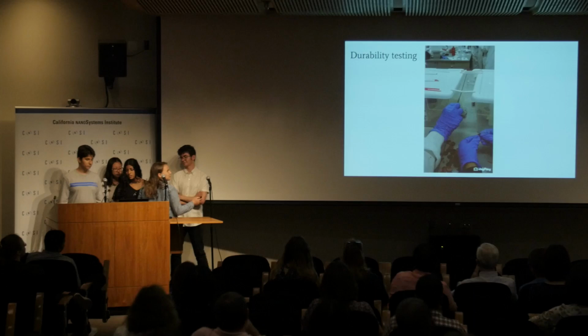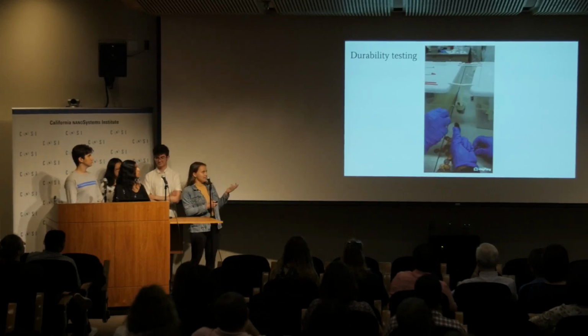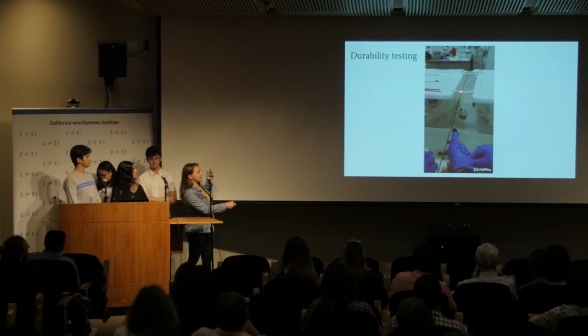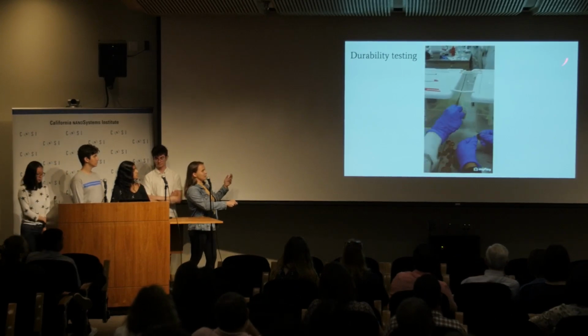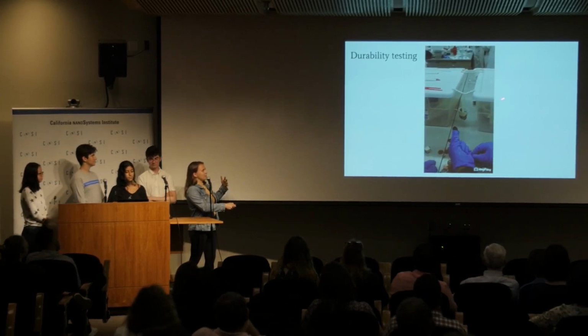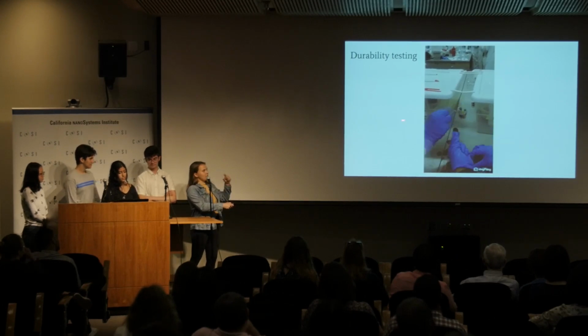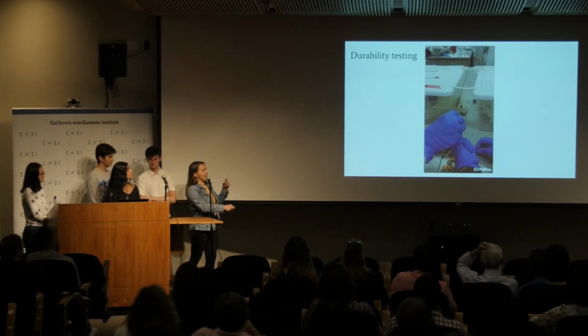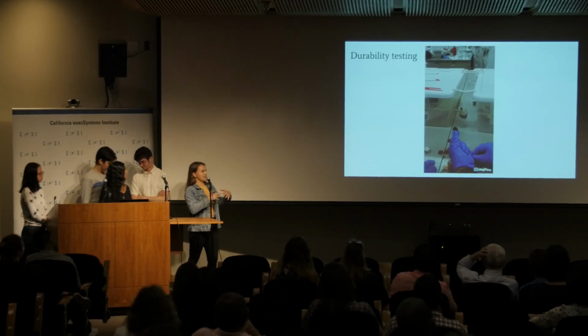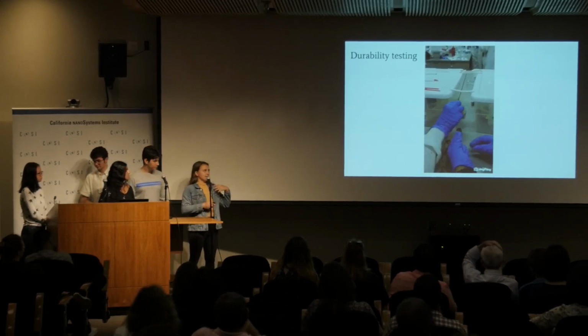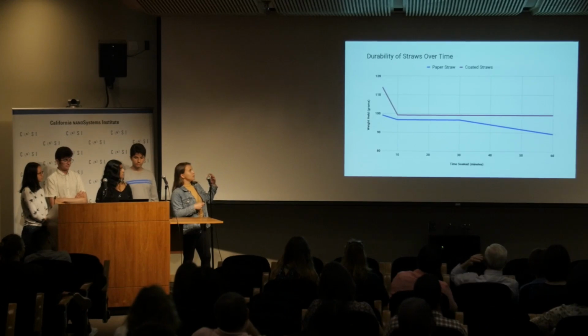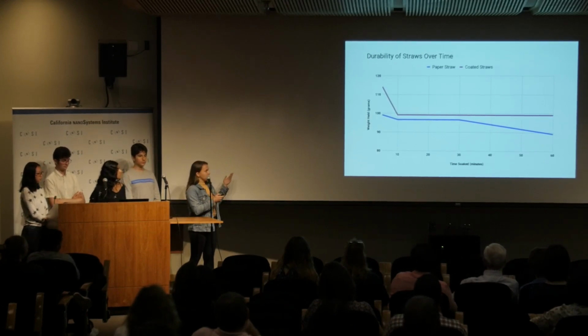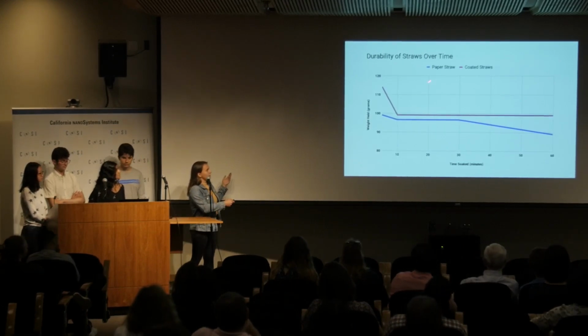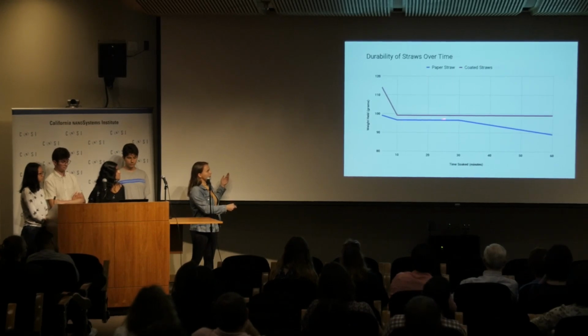So I'm going to take a closer look at the actual durability testing. Here we see that there is this straw, and we made some sort of basket contraption and placed pennies into it, and we have the weight of the pennies and the weight of the basket, and that pretty much tells us the amount of weight that this straw can handle, which in turn tells us the durability. So using this testing technique, we got this data, and we pretty much see that paper straws and coated straws here both have a very similar durability, from 10 minutes soaked in water to 30 minutes soaked in water.